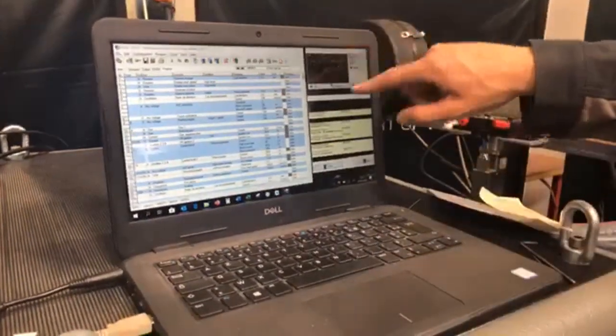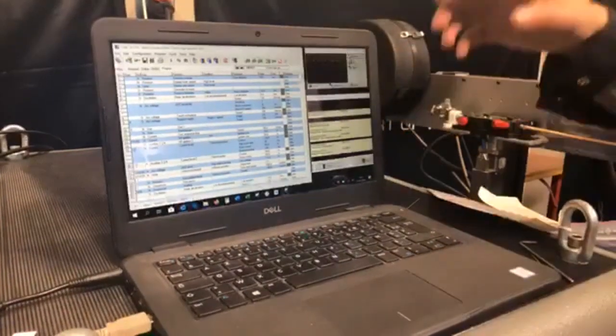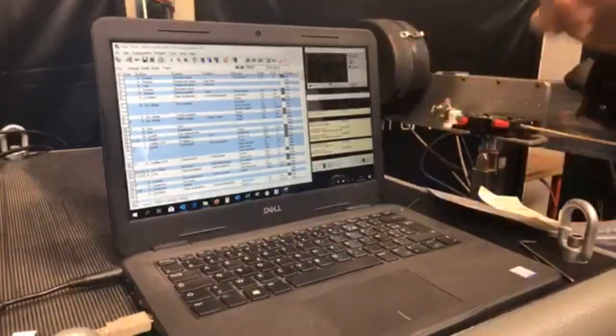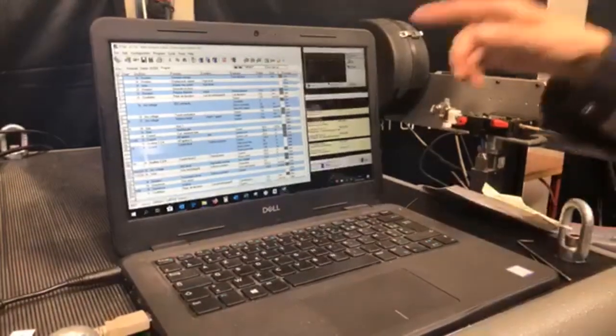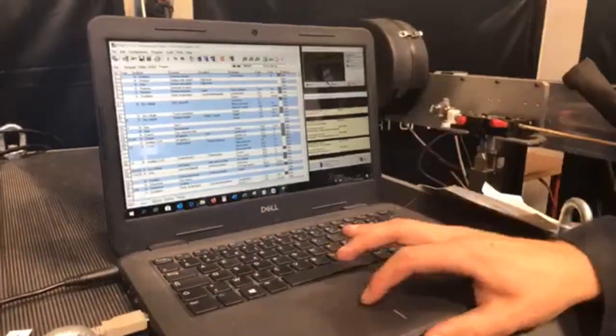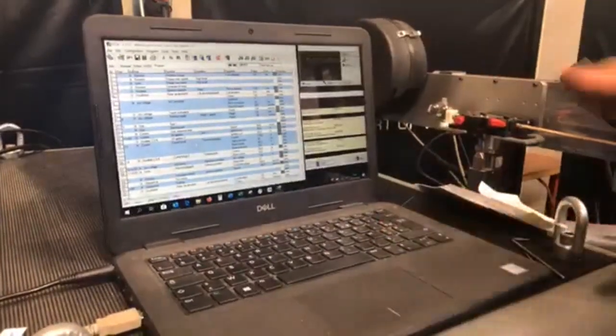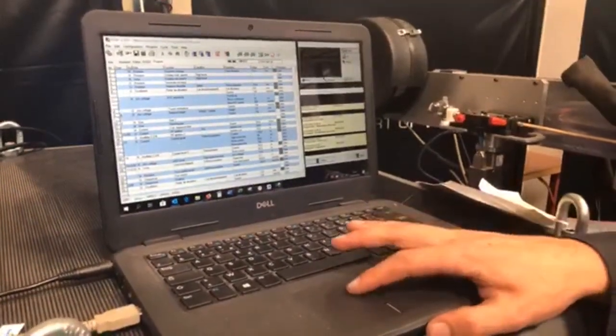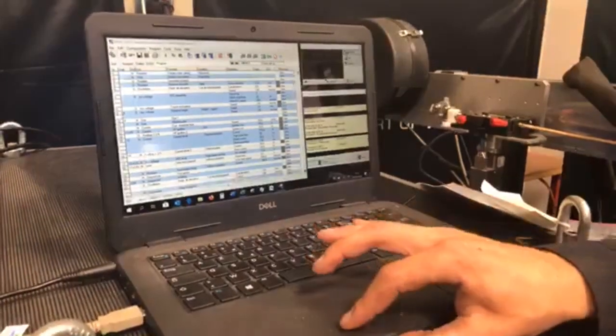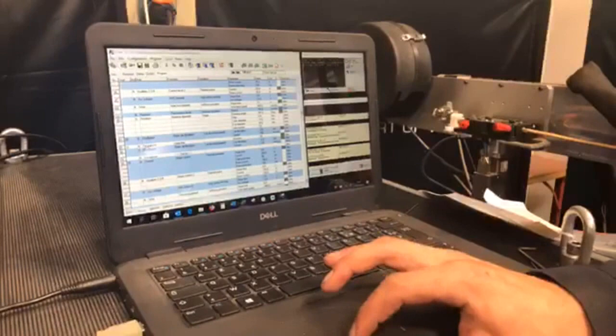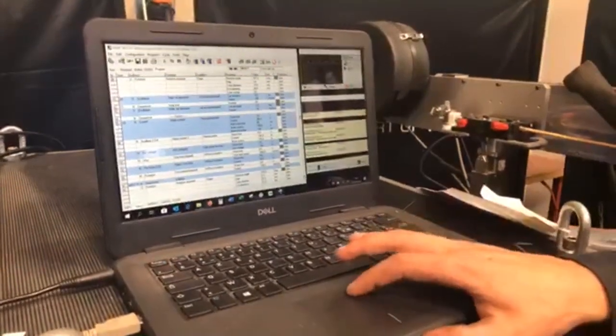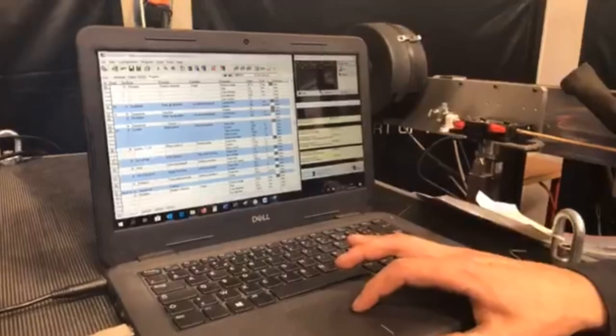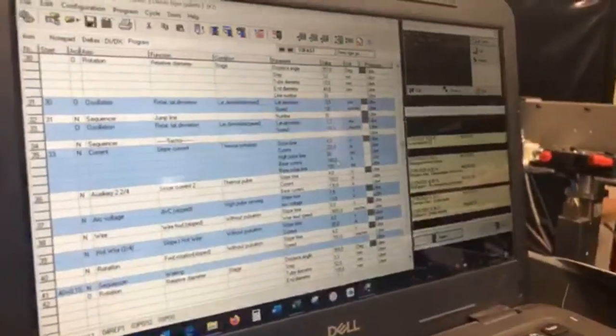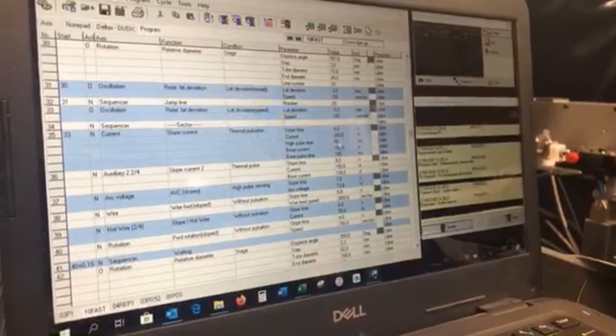Okay. So here, this is what you can see during the welding. So the speed of the wire, the speed of the rotation, the current, tension, and here you have all the programs. So it's line by line. You can find the current. So here, if we go down, okay, we can see the current here is 200 amps and the base current is 180 amps. Okay. The pulse is 50 milliseconds for the high current and 100 milliseconds for the base current.